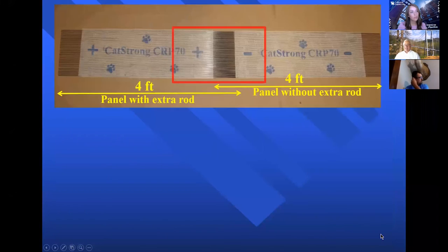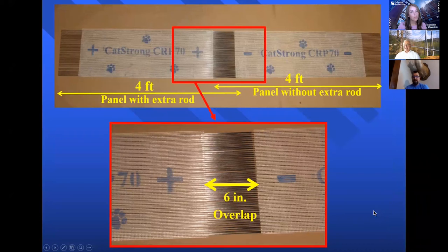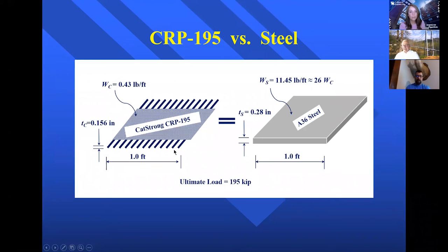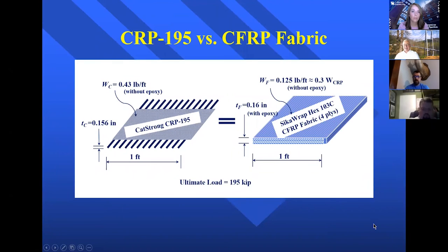So now I can be hanging from a bucket truck over a waterway, strengthening the underside of a bridge with these things. It's an extremely effective method for repair, and we did extensive laboratory testing on it in our lab, primarily to evaluate this finger joint. And to give you an idea, our strongest panel can carry 195,000 pounds in a foot width. This is equivalent to a steel plate that weighs 26 times as much as the rod panel. And so, of course, quite a bit of an advantage.